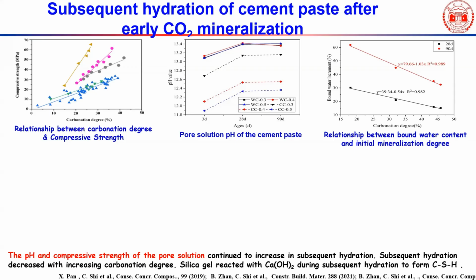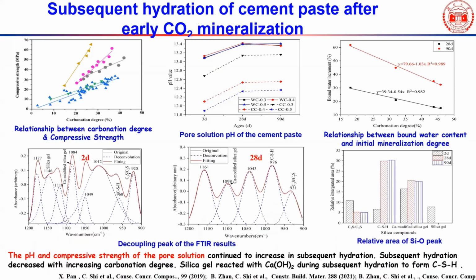And usually, when the pH is above 11, a passivation layer will form at the surface of a rebar. So in that way, you are sure the carbon mineralized product will not cause a steel corrosion issue. Of course, the higher the initial carbonation degree, the lower the hydration degree and the chemically combined water, and that we can understand.